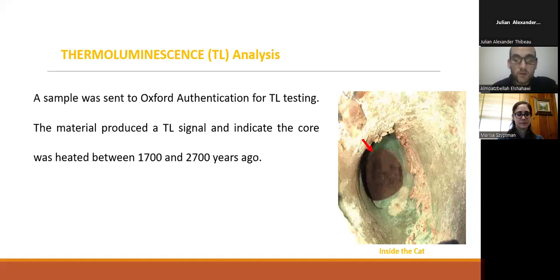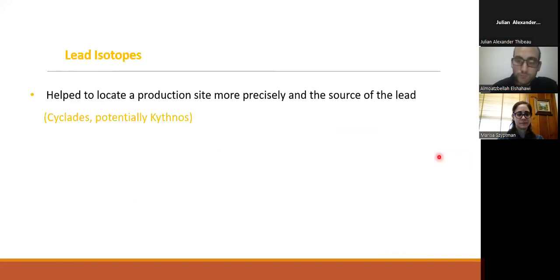Taken together, the alloy and clay core date point to the cat being an ancient Egyptian work after all. The study of characteristic lead isotopes helped to locate a production site more precisely and the source of the lead. As for the source of the lead, Patrick from the Oxford lab was able to run the lead and copper samples, and Monica Gennaro from conservation at the GCI did some interpretation based on the database in Oxford.